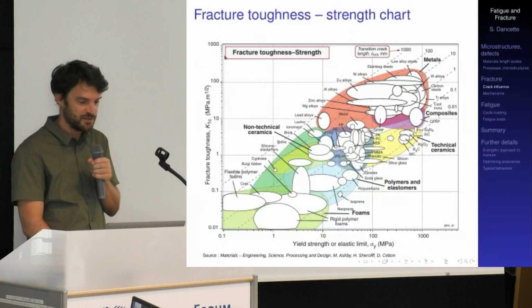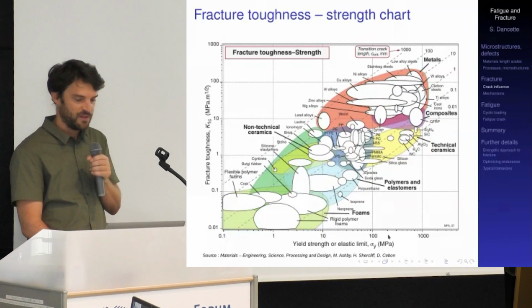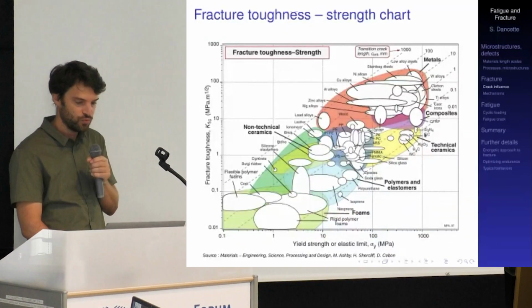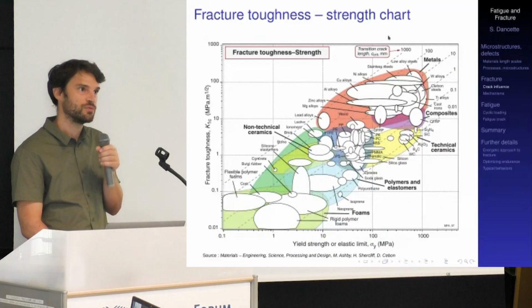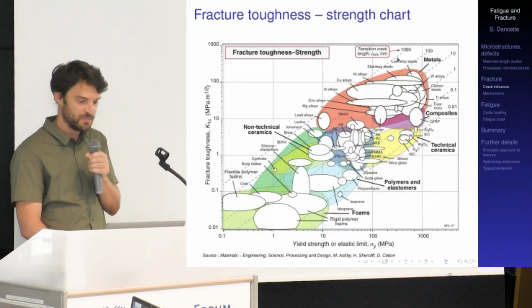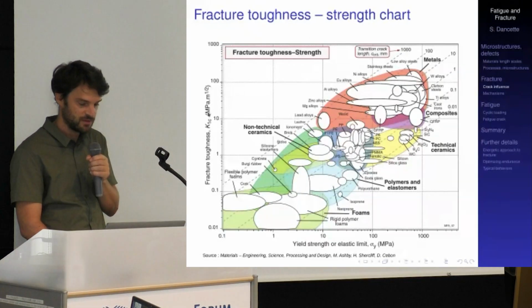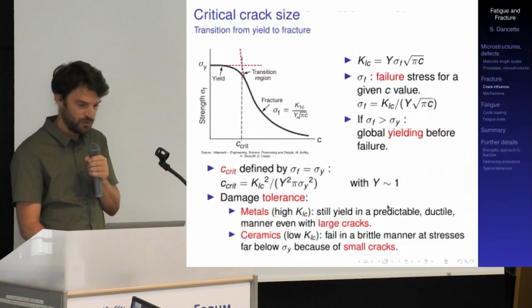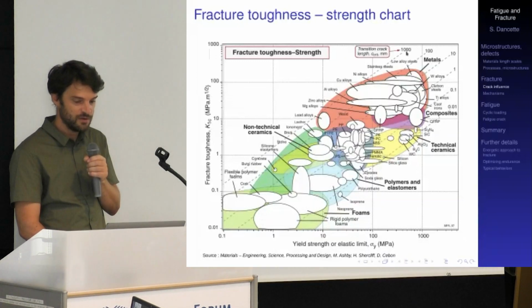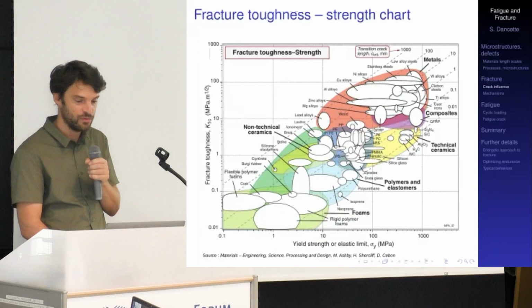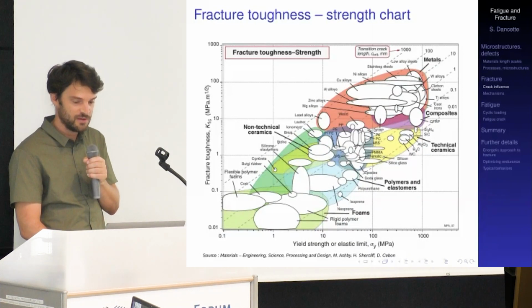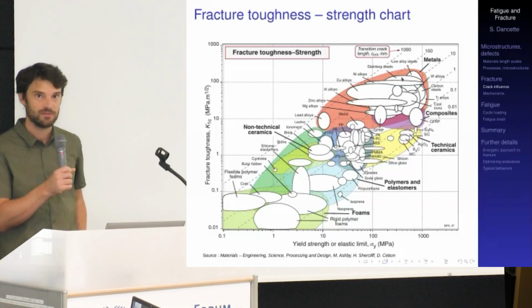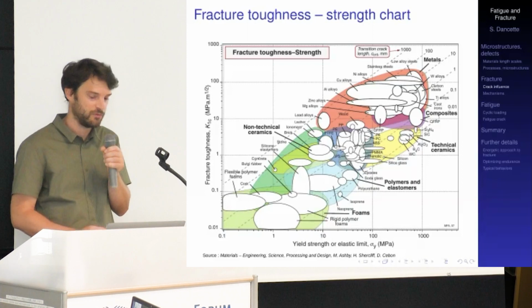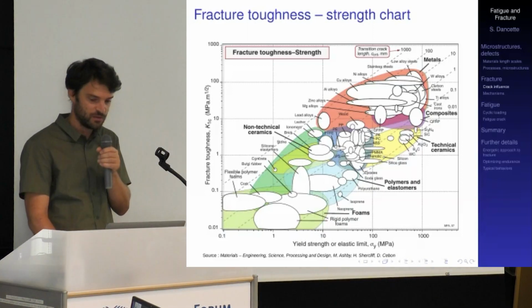And again, if you use these charts here of fracture toughness as a function of yield strength, then you come up again with an easy way to assess the orders of magnitude of the critical crack size in the materials. With materials such as metals with a very high fracture toughness and moderate yield strength, the critical crack size might be as high as a few tens, a few hundreds, or even a few thousands of millimeters. So it is not unusual to find defects on the order of millimeters in metals. In most pieces, these defects are not detrimental in service properties, at least static service properties.